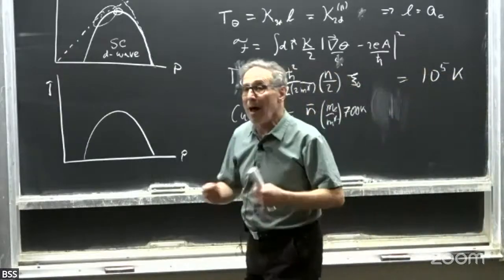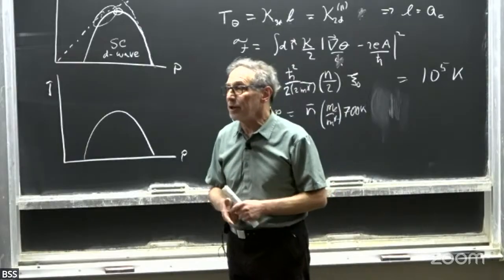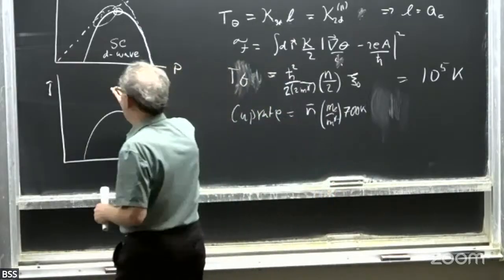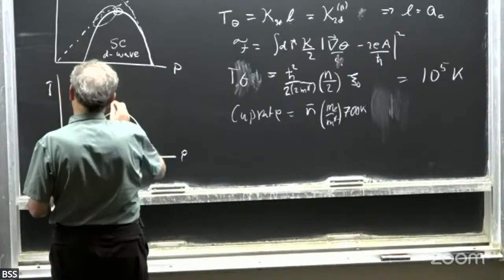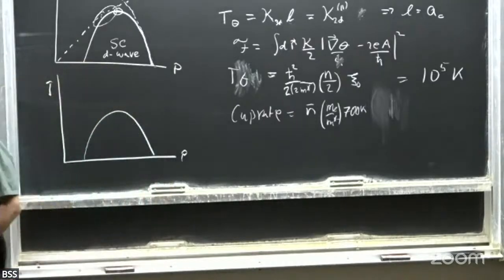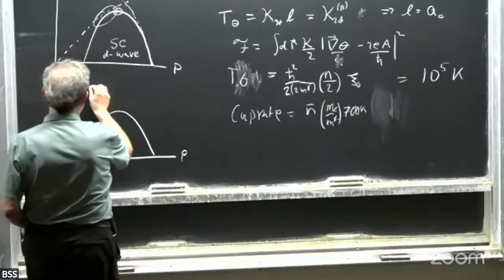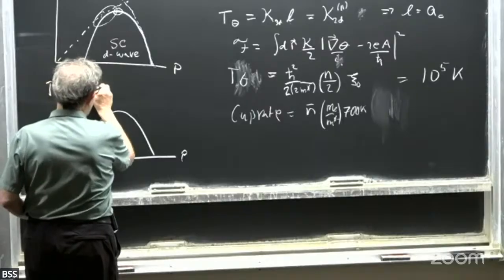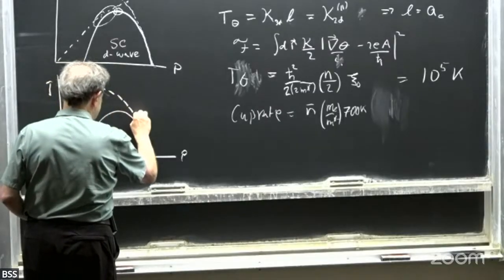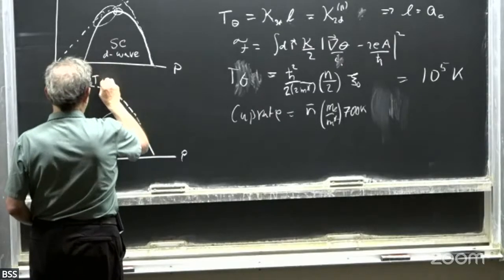And you can plot that amplitude as a function of doping. And if you do that, unfortunately, there are some differences in exactly what number people extract. And I don't think it's actually due to differences in data. I think it's differences in data analysis. But no matter how you do it, you come out with qualitatively the same thing, which is that you have something that goes like this.